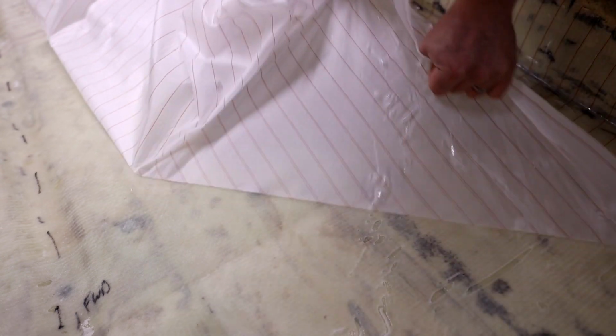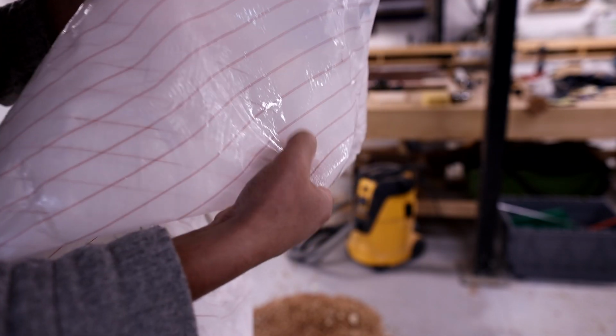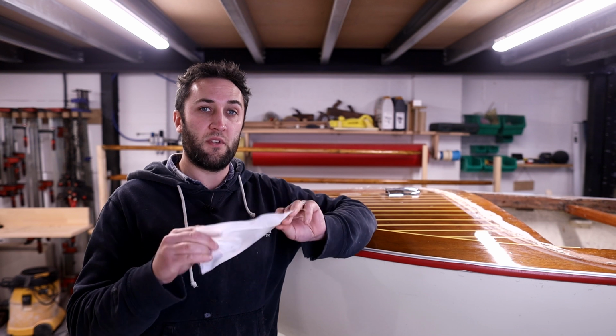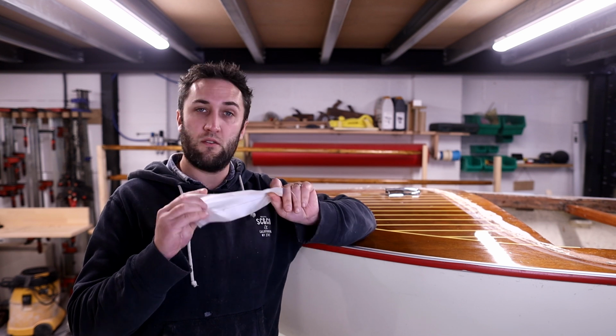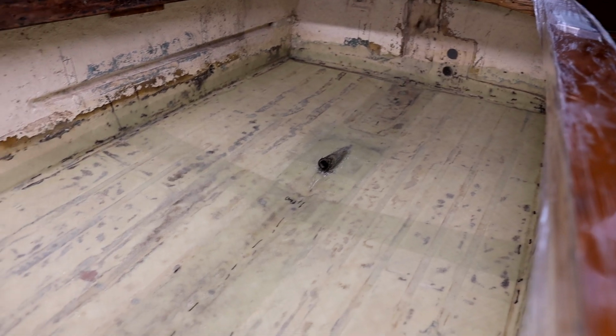That also has a byproduct of protecting the integrity of your glass. Because the surface is already keyed and free of amine blush, you don't need to sand the surface, which means you're not likely to sand into the glass and damage the structural integrity of what you've just created. So it's an extra process in the layup stage, but I highly recommend it because as soon as it's peeled away, you've got a perfect, clean, nice flat surface to continue working on. So it massively saves on the afterwork for stages that follow.